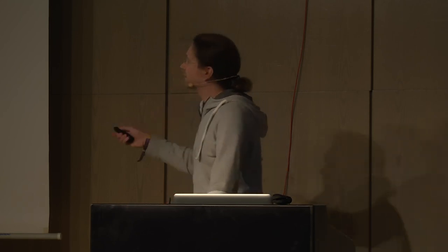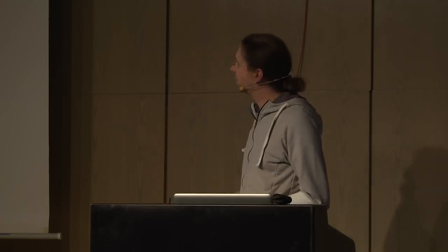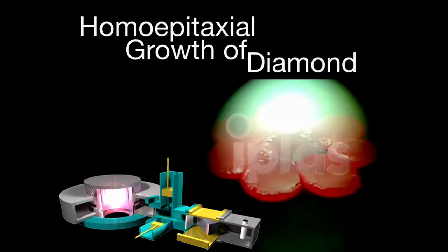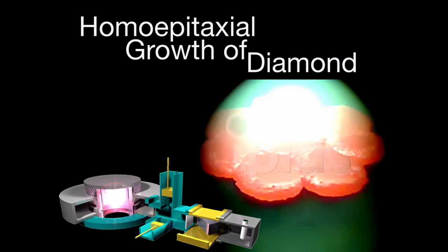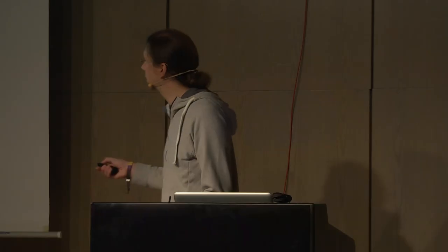Okay, this is a movie. Let's see how these diamonds are growing. Unfortunately, this is in the course of 3 days, Friday evening till Monday evening. Those diamonds don't look very nicely. Now they are 3 millimeters tall, so they're rather large size diamonds. Perfectly single crystals in the middle, not so perfect and not good looking in the outer edge here.